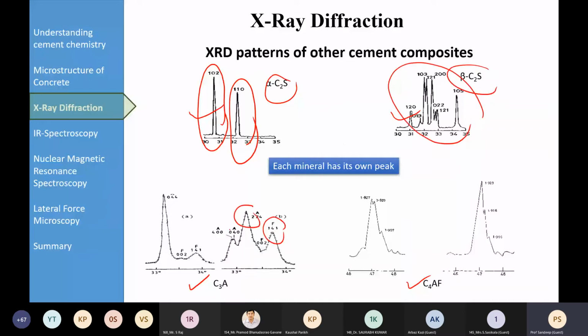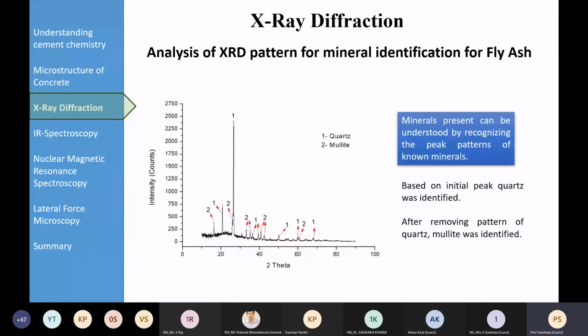each mineral. Here typically this is an analysis of XRD pattern for fly ash, which was done in our laboratory only. So here you can see easily that this is the most dominant phase, quartz, and then this quartz is present at other angles also. So quartz is there, and then mullite is there. 2 is mullite. So along with quartz, there is mullite. Of course, quartz is also predominantly available at this angle, but then it is present at different angles also. Similarly, mullite is also predominantly available at this angle, but then it is present at different angles also.